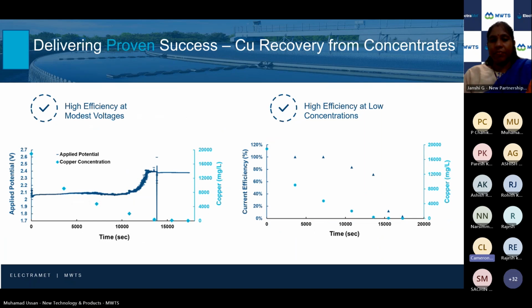And taking on the other side, the extreme side, the wet etch and electrochemical plating, the higher concentrates, we can now use this combination of our electrochemical reactors to go from very high concentration down to environmental compliance. And we can do this very efficiently from an energy standpoint, but also very efficiently in terms of time and labor. On the plot on the left here, we're looking at the voltage you apply over time as the copper is removed from this concentrate. We're doing this to find the optimized concentration to switch from one reactor to the next, so it's best suited for those operations.